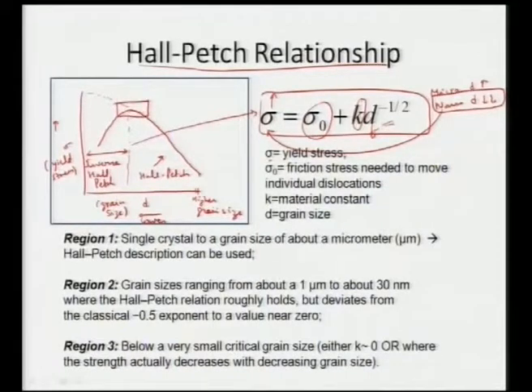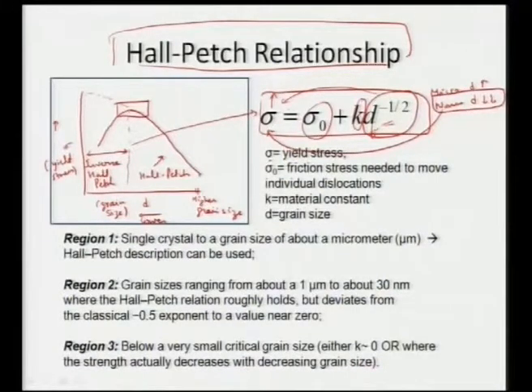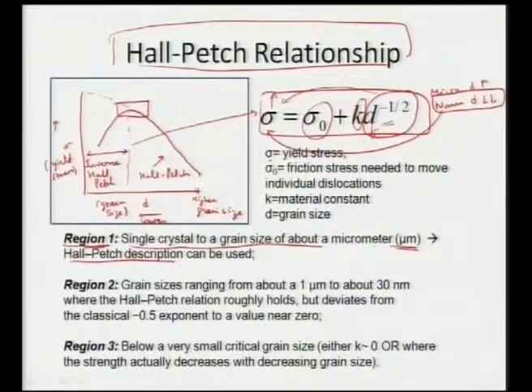This region of inverse Hall-Petch is also a region of concern. The Hall-Petch relationship states that σ = σ₀ + k·d^(−1/2), so as we start decreasing the grain size we should see an increase in the yield stress. There are three regions of concern: Region 1 is where we have well-behaved Hall-Petch description — the Hall-Petch relation is maintained for single crystals to a grain size of about 1 micrometer, meaning σ is really dependent on d^(−1/2).